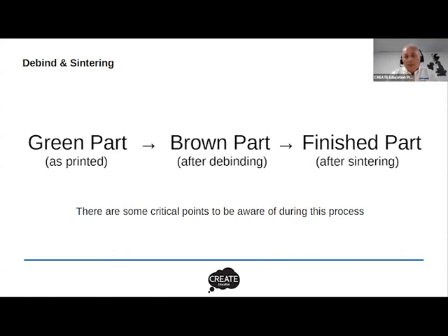It then goes into a sintering furnace, and the sintering furnace involves temperatures ultimately up to around 1300 to 1400 degrees centigrade to fuse the metal powder together. And there are some critical points to be aware of during this whole process. And one of those critical ones occurs in the early part of the sintering stage. And that's often called the valley of death.